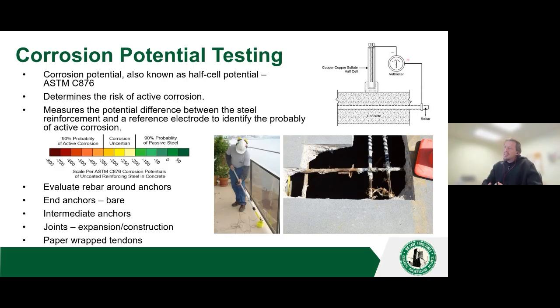So what this test does is it tells us the probability of active corrosion in bare mild reinforcing steel or in anchorages or paper wrapped tendon. Since a paper wrapped tendon isn't an electrically isolated tendon, we can test the long length of a paper wrapped tendon to see if there's active corrosion going on, just like we would a rebar. So this is a good test around rebar or anchorages, right?